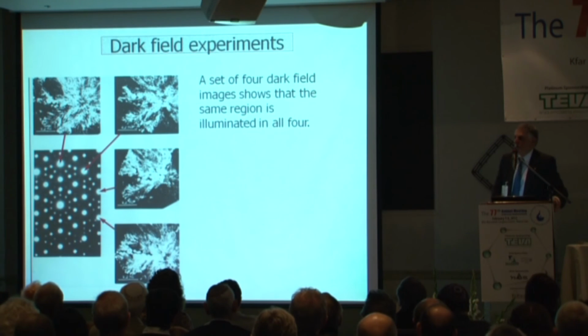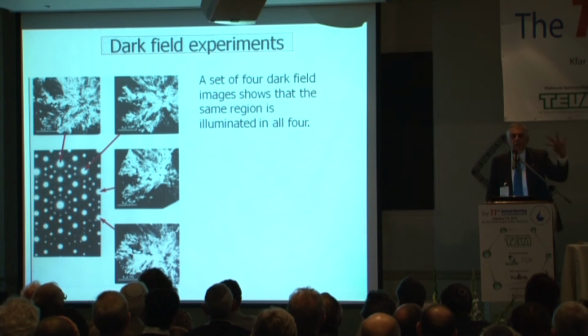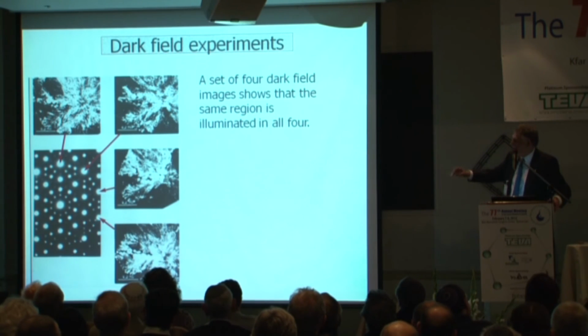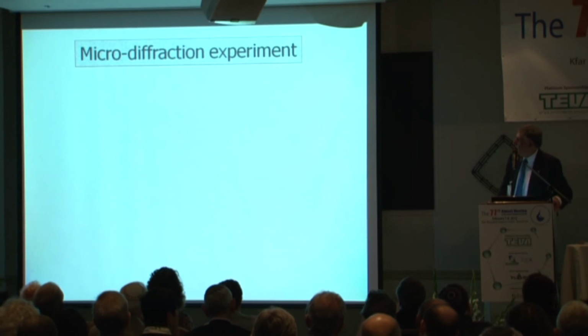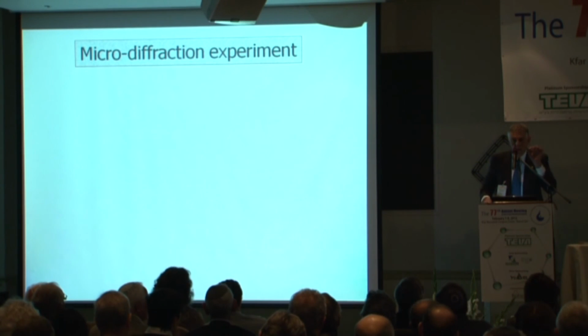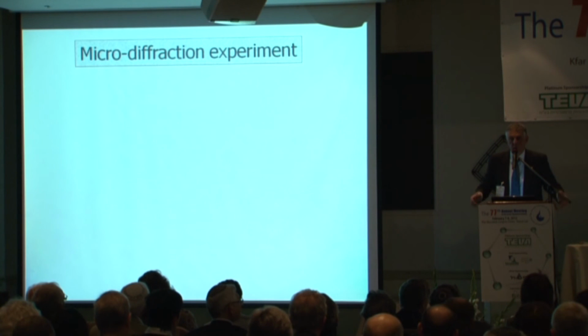I don't think we have time to go into details of how we do that, but it was meant to show the different twins. As I have shown you in the previous picture, you see clearly the different twins, but using many diffraction spots to take the dark field images, I could not find the twins. And so I said, well, maybe the twins are too small, below the resolution of the microscope. Maybe I'll do another experiment called convergent beam electron diffraction. When you do that in an electron microscope, you converge your beam onto the smallest spot you can, and take a diffraction pattern from that spot. The minimum spot size on that microscope, a Philips 400, was 400 angstroms, or 40 nanometers.